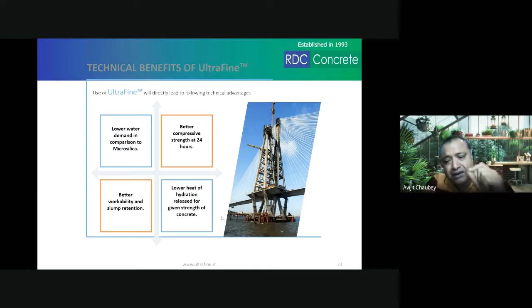Finer particles are good only if they are used to fill between the gaps. But if the gaps are much bigger and the particles are much smaller than the gaps between the bigger size aggregates or bigger size cement particles, then this will actually create a disadvantage. So it should be not too fine, but just fine, so that you are able to get the good type of workability and strength.